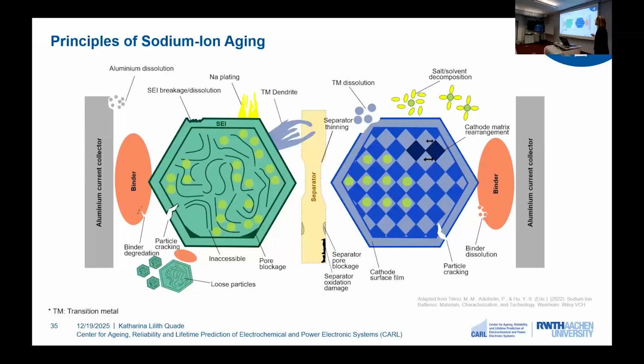Another important aging phenomenon is the so-called sodium plating. This can happen when the anode cannot fully accommodate the sodium, and it's more favorable for the sodium to plate on the surface of our anode. And this, as you can see here, can have dendritic structures. These can then penetrate the separator and lead to short circuits.